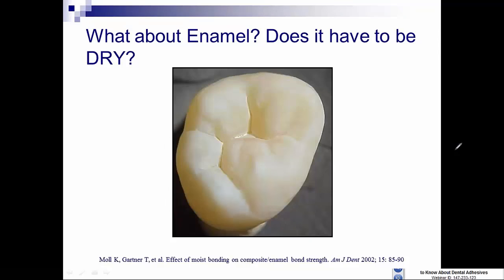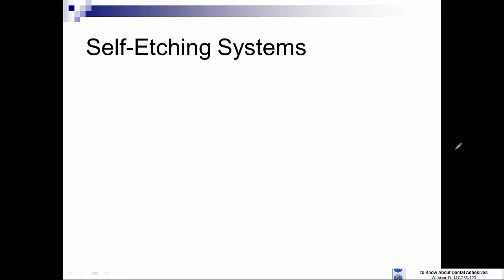So what about enamel? Does enamel have to be overdried? And the answer is, if the same level of visible moisture that we see in moist dentin remains on enamel, these bonding agents, these ethanol and acetone and tertiary butanol containing bonding agents, are just as effective in bonding to moist enamel. However, it's an excellent clinical tip to look at a surface like this, if you're believing that you have mostly or only enamel, and vigorously air dry it, because once etched enamel is dried, one can easily see if there is residual protein or debris on the tooth that has prevented full interpenetration and etching.